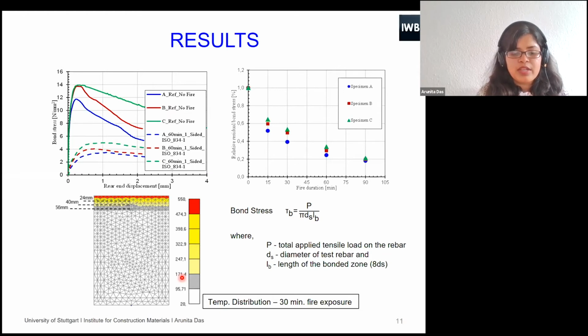This is a very key point in our study, that the temperature gradient is playing a key role. When the top surface is reaching around 500 or 600 degrees, the bond surface is still almost cooled down, or around 150 to 200 degrees. So there is a huge temperature gradient, and due to that there is a huge concrete crack. Once there is a crack, the bond strength goes down drastically.